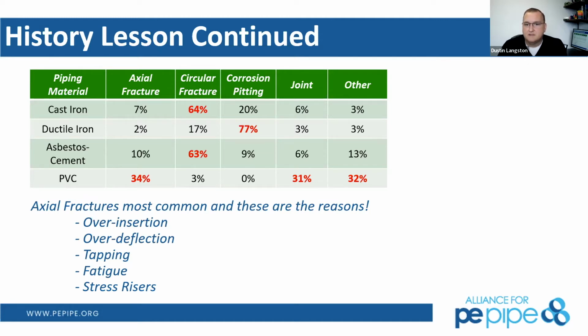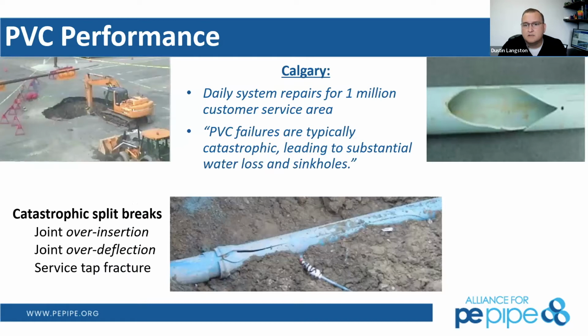PVC, this is a completely different type of failure that we're starting to see with PVC pipe that's never really been seen in the water market before. And we'll talk a little bit more about this at the end of the presentation. But we don't really have the circular fractures. Obviously, there's no corrosion. Same with polyethylene, no corrosion. But axial fractures have become the new failure type that we really need to talk about. And a lot of these failures are from poor installation. Flat out, PVC can have a very long service life if it's designed and especially installed correctly.